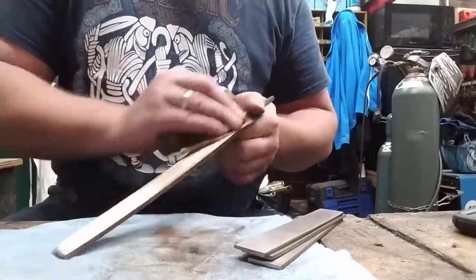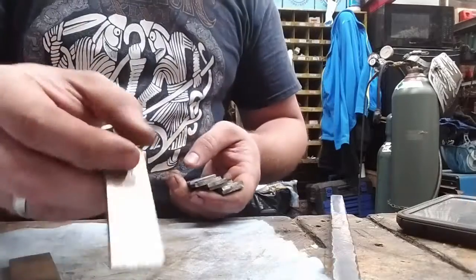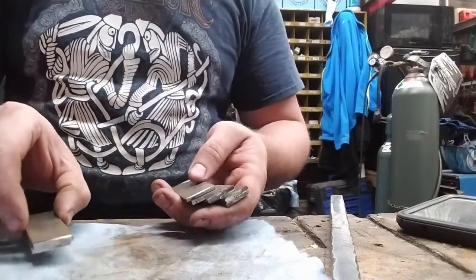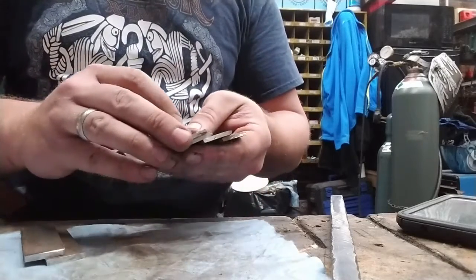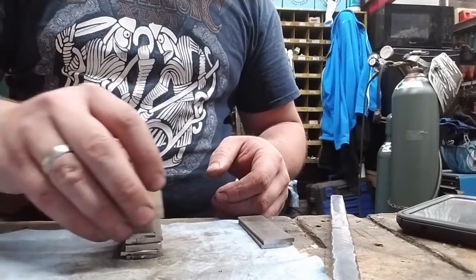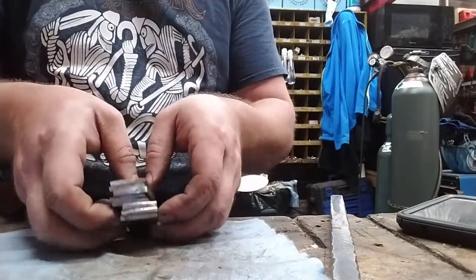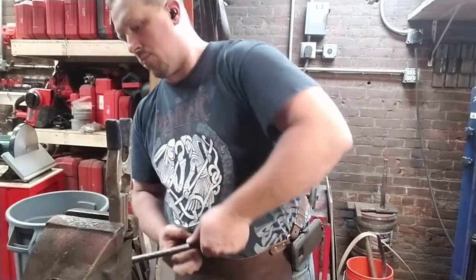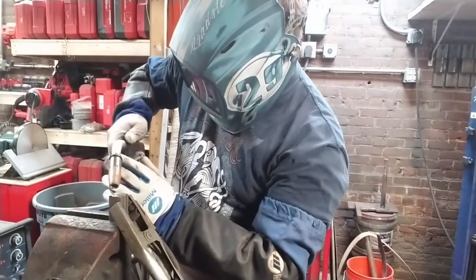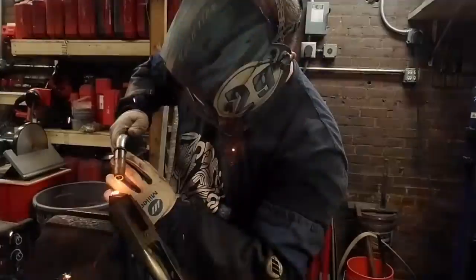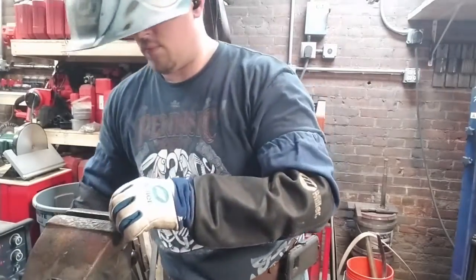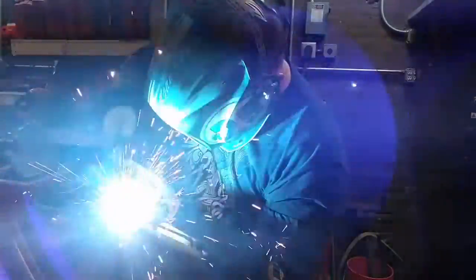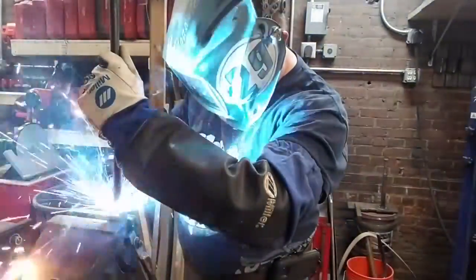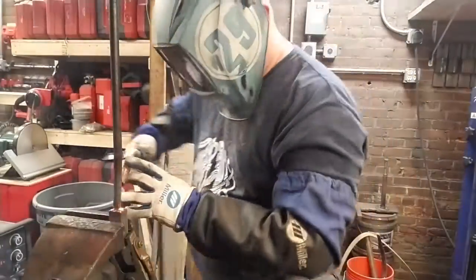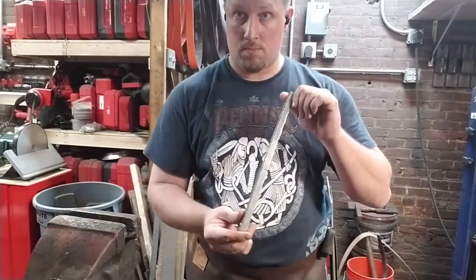And we have a little bit of known good donor material in the form of this Nicholson Black Diamond file. And that's a very period process, not necessarily using files as a parent material, but using known good and no longer necessary pieces of iron as a moderating factor when adding new steel. Because we don't know the characteristics of the steel that we made. It may be very high carbon steel, overly high carbon, or it might be medium carbon and not as much carbon as we need. Now, honestly, from the spark test, I think we have some really good stuff. But regardless, either way, the material of the file will be a moderating influence and should probably improve it one way or the other. So we're making a simple little billet here, and as soon as we get it all welded up, we'll toss it in the forge.